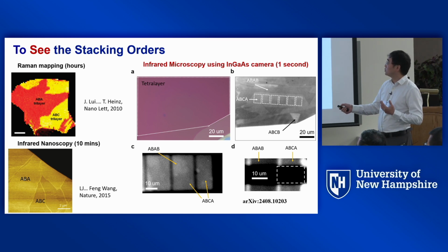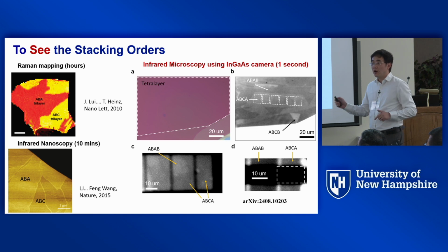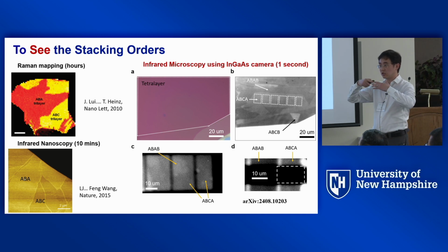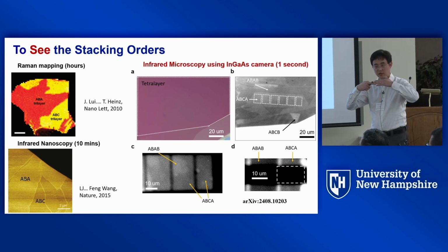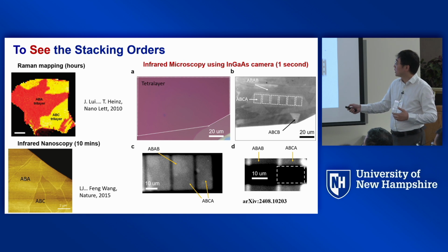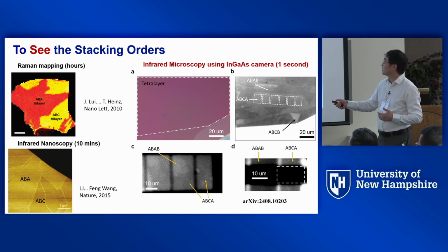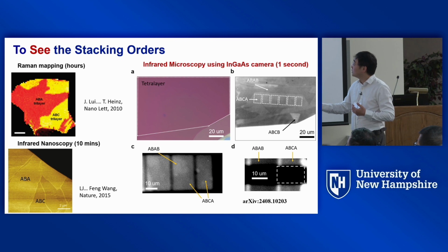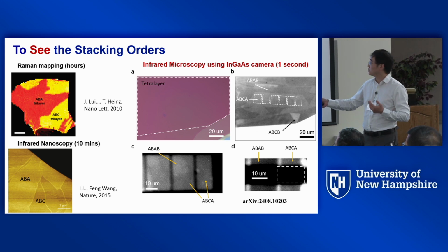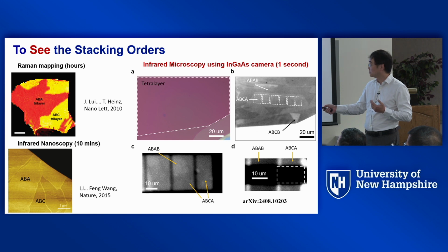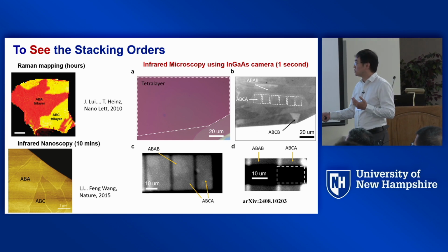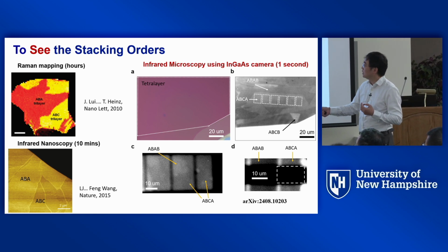One way you can do that is Raman spectroscopy, looking at a particular Raman peak that is sensitive to the phonon structures, which depend on the stacking order. You can tell the ABA and ABC regions, like what Tony did more than 10 years ago. And if you can map the whole flake, spanning a few hours, you'll be able to tell where's ABA and where's ABC.